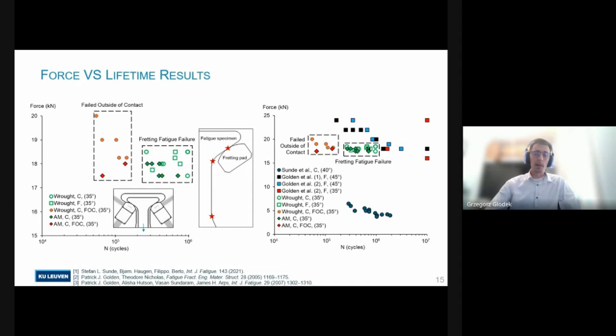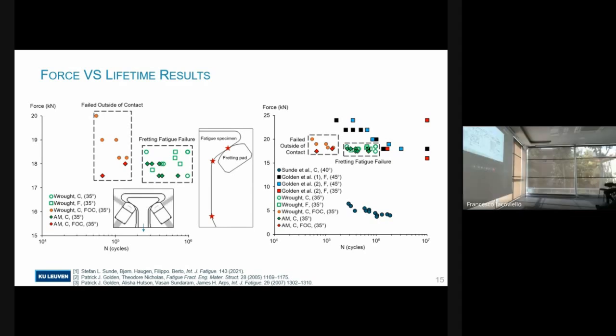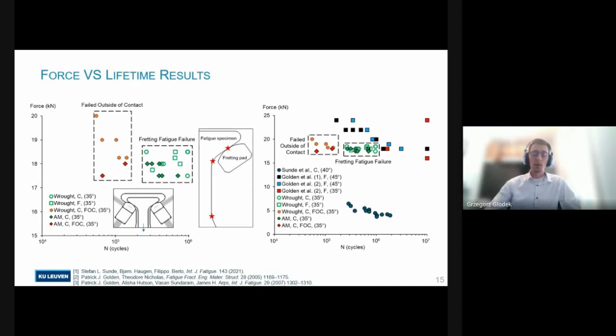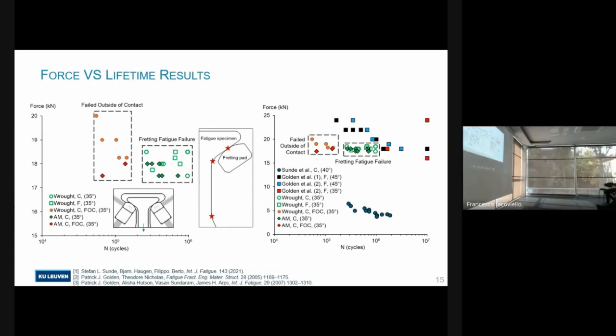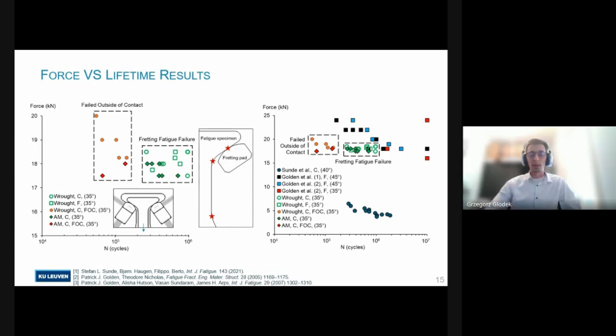So in order to better gauge the response of the additively manufactured Ti-64 compared with the wrought material, data from literature was extracted as well and is plotted here. It's for the same dovetail setup and also the same material. But comparing it using force is not very representative, since we're dealing with different contact geometries, different sample geometries as well. Therefore, those models were recreated in finite element software to use more local parameters for that comparison.